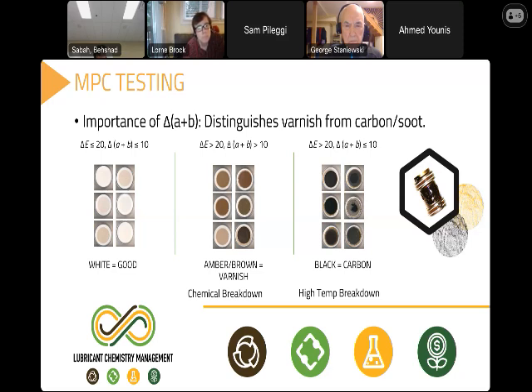The other thing that's interesting about this is it's only telling us color. So we don't know concentration. So we like to weigh the patch, only takes an extra 5 seconds, and then we can measure the grams, the milligrams it is, and then we know, oh, is this a high concentration or a low concentration? That's one extra thing that the labs can do that's really beneficial.